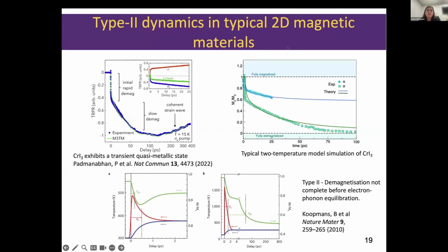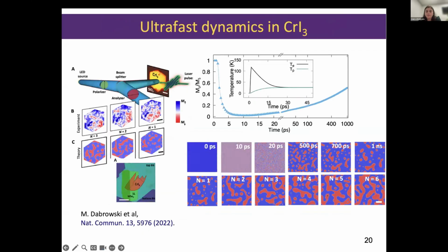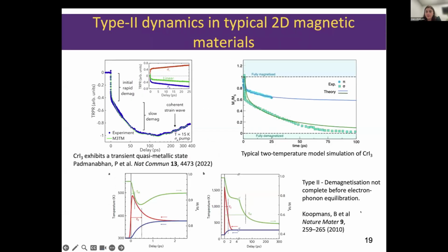Most of these 2D magnetic materials show what's called a type 2 demagnetization process. This was introduced by Dr. Bert Koopmans et al., where essentially your demagnetization process happens in two steps. First, there is a quick demagnetization coming from the laser pulse, and then a slower decay of your magnetization coming from the elevated phonon temperature. And most of these 2D magnetic materials show this type 2 demagnetization.